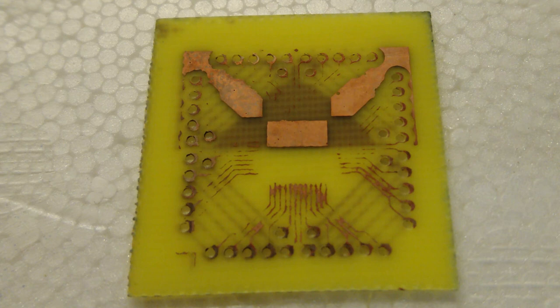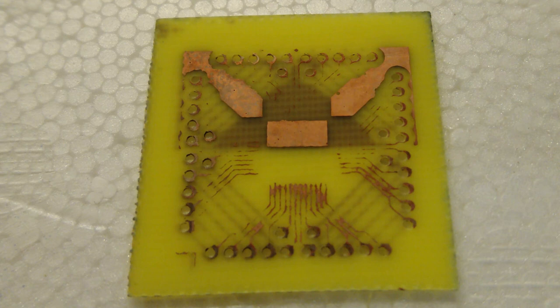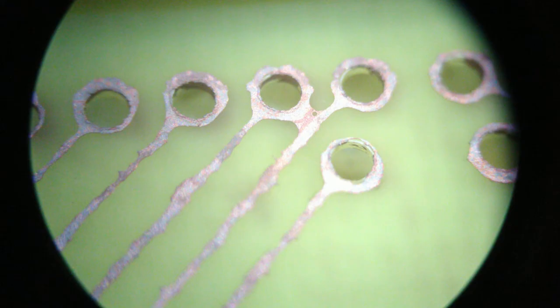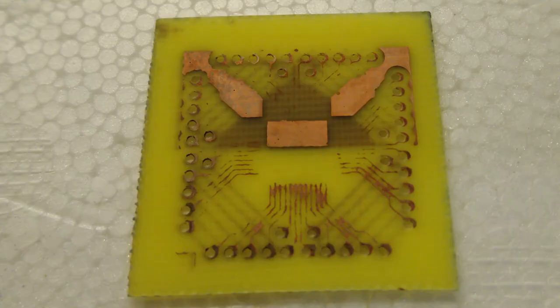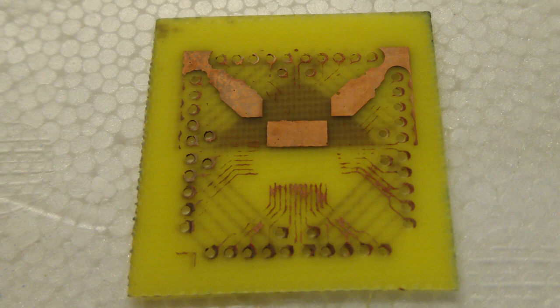A detail under the microscope shows that some tracks dissolved and some shorts remain, but also that some copper remained in the holes after the etching. I performed a test with a multimeter, and 48% of holes have electrical continuity. This is the first time I get more than 0% of holes with electrical continuity. So, while it's still a failure, at least I'm making progress.